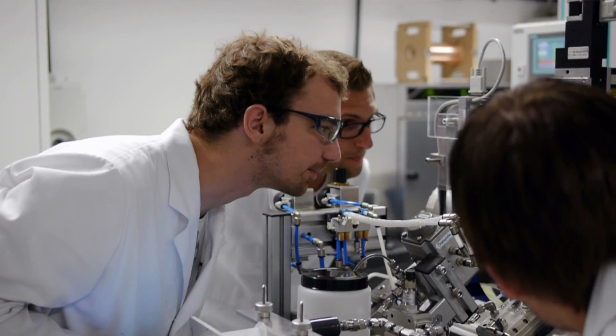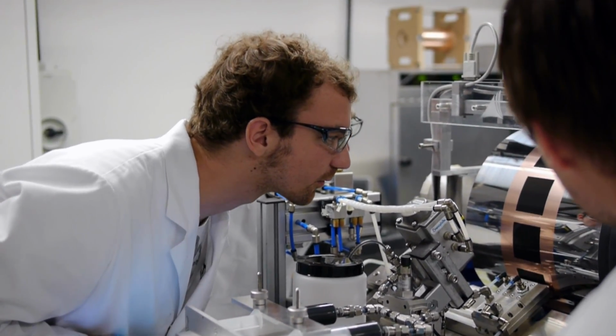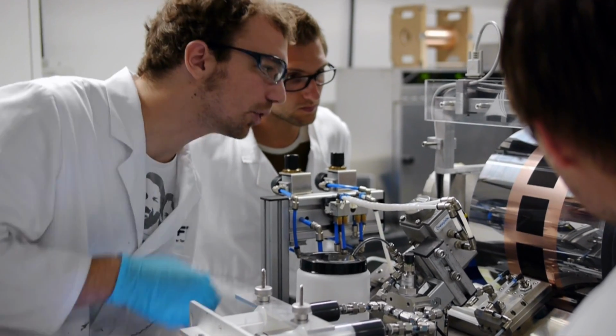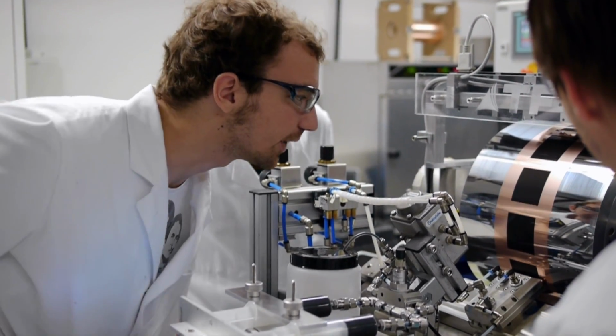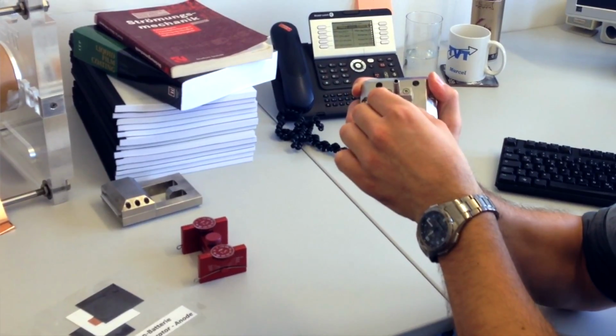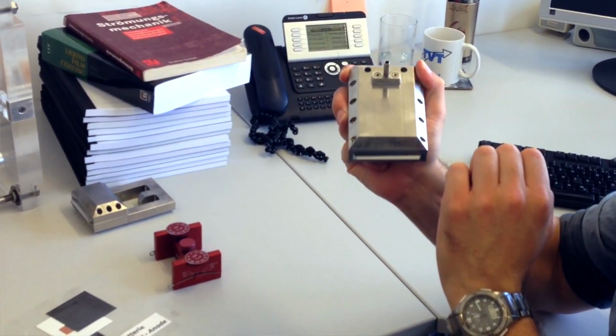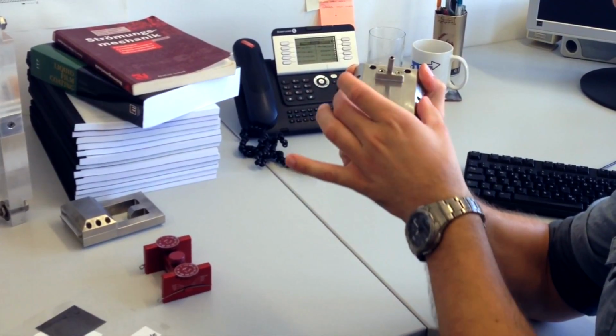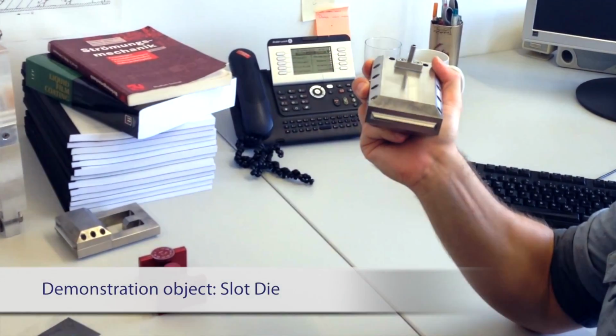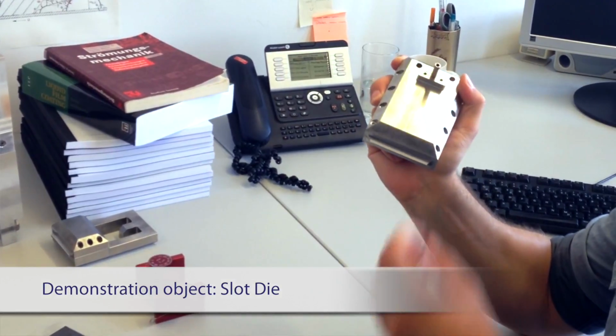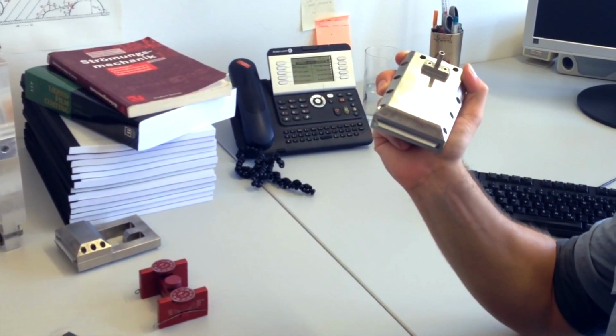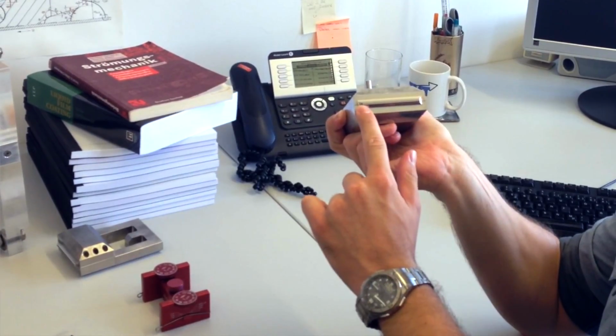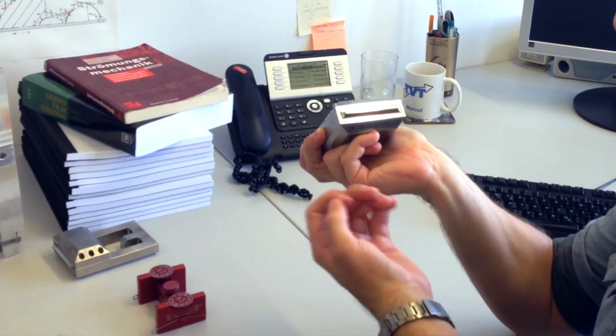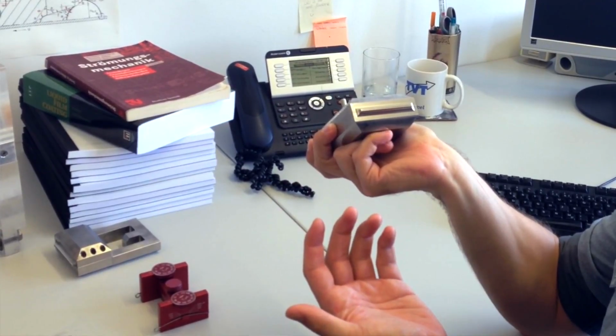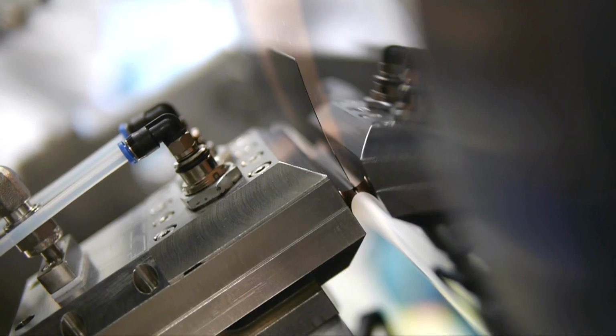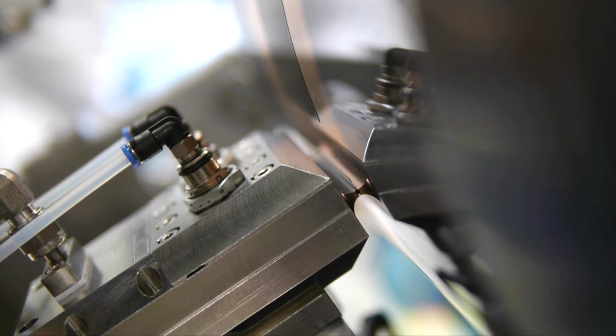My research topic is the coating of these slurries onto the metal foil. Being more precise, we use a pre-metered coating method, like the slot die coating. Here you have an inlet where you give a very defined liquid flow. You have a distribution chamber and a small slot where you get a pressure drop. And within this pressure drop, we get a good distribution of the liquid flow over the slot width. And here it's really important to form a stable coating bead between the die lips and the substrate you want to coat on. This coating bead forms your film and has to be stable.